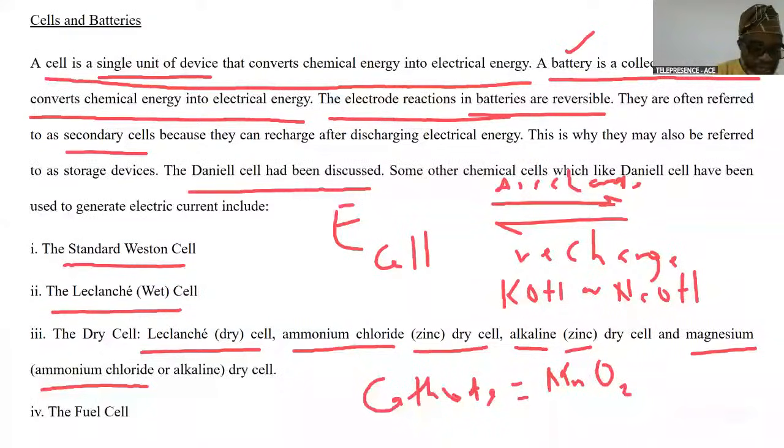This is the formation of a complex ion. The complex ion crystallizes as a white salt. For some of you who are familiar with the Tiger battery, after prolonged use you find at the negative plate of the cell some white crystals, and that white crystal is zinc diammine chloride. The zinc ion can take up the ammonia. As you know, ammonium chloride is the source of the chloride ion, to produce this white crystal.